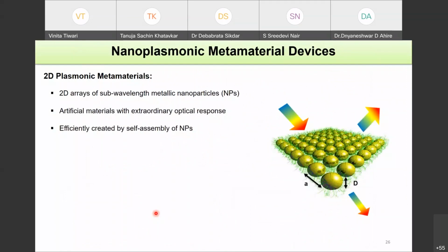Now moving on to plasmonic metamaterial devices, where you have many such nanoparticles forming a 2D array which is basically sub-wavelength in size. Now, what do you mean by sub-wavelength? That each nanoparticle is also much smaller than the wavelength of light, and the interparticle separation is also much smaller. So what happens? These nanoparticles can effectively behave like a different or a unique layer, and it has a very different metallic property than the constituent material. And one good thing is that they not only give extraordinary optical properties, they can also be efficiently created by self-assembly of nanoparticles. So you do not need to do top-down fabrication. You can use very inexpensive methodology of self-assembly.